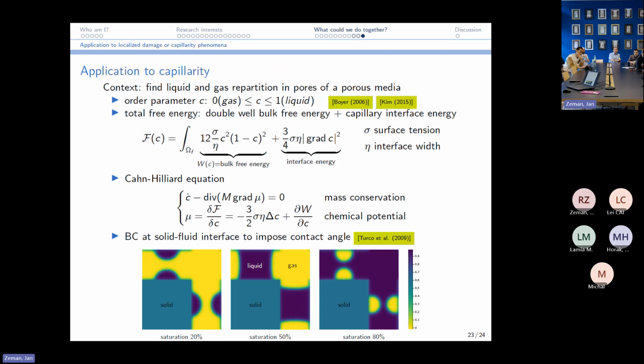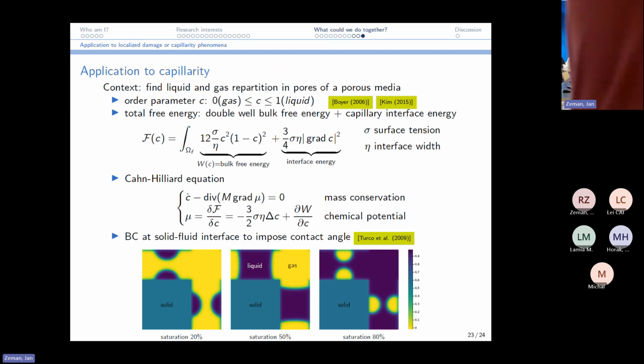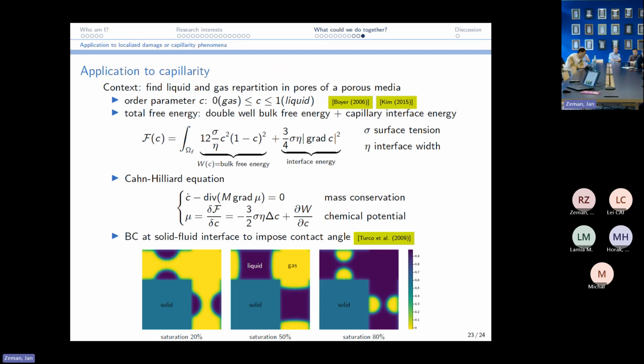And for that, we could use, for example, a Cahn-Hilliard type formulation where you have a smeared interface energy with some regularization parameter eta. And so I did some experiments on the periodic domain where you have a square solid and then it repeats periodically. And here you have the pore. And then as you increase the water content, first you will have drops, then these drops will form bridges. And then if you have too much water, these bridges will collapse and you have only some air bubbles in the end. So that's something I would like to do.